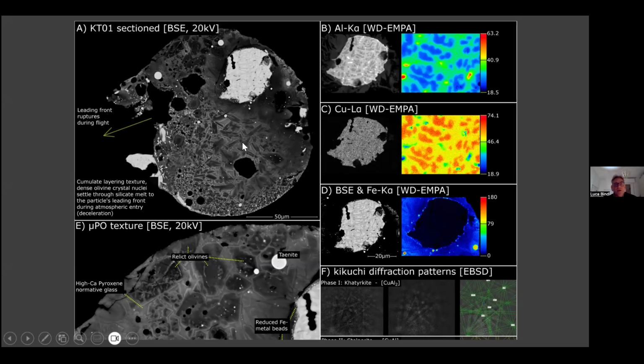You can see here relic olivine, silicate glass. Look at the chemical maps, of course. And you look at this blow up here. What is very interesting is that they also carried out electron backscatter diffraction analysis to see that the copper aluminum alloys were actually exactly what we reported in the Khatyrka meteorite.